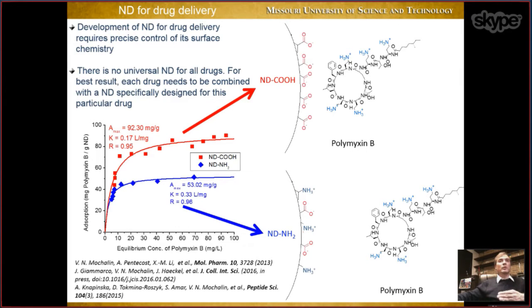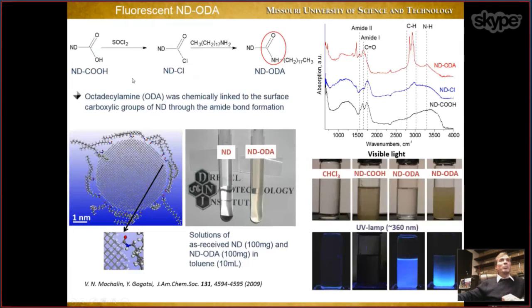One has to pay attention also to other properties, such as surface chemistry, for example. We can also make this material fluorescent by attaching long chain amines to the surface of nanodiamond. This is how we do it. And of course, since this material has long hydrocarbon chains on the nanodiamond surface, it behaves as a strongly hydrophobic material.